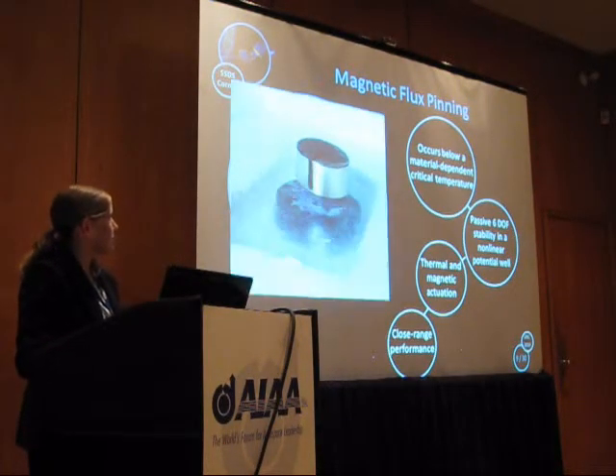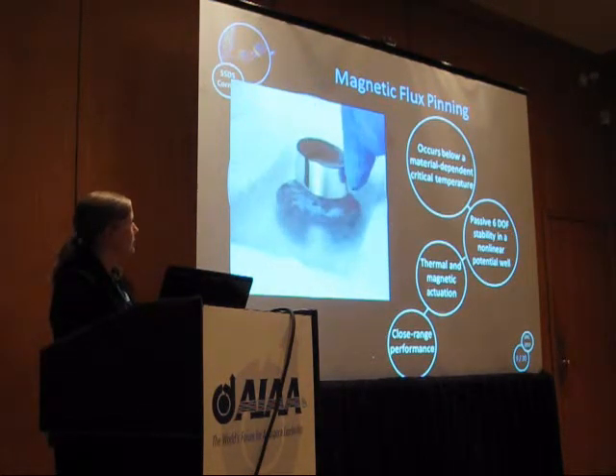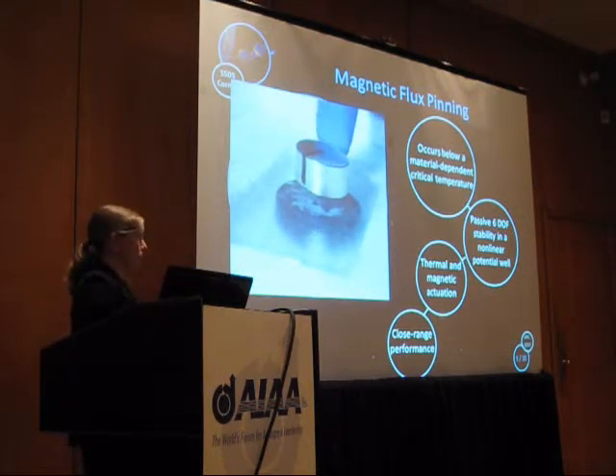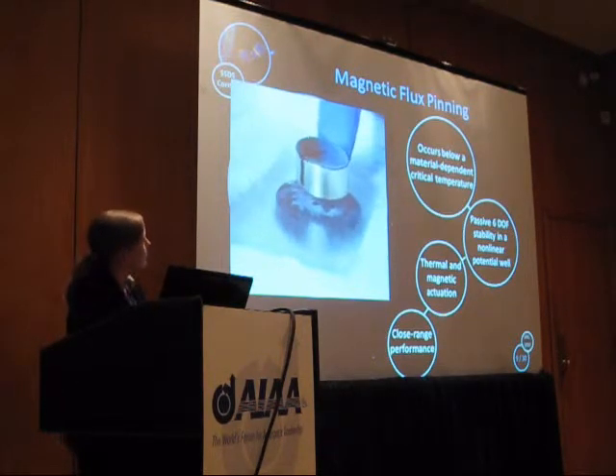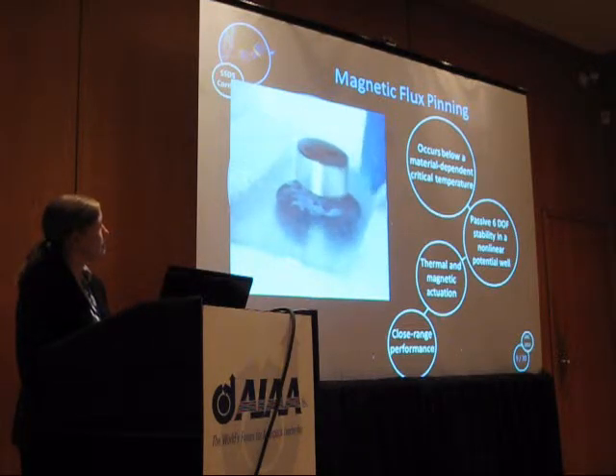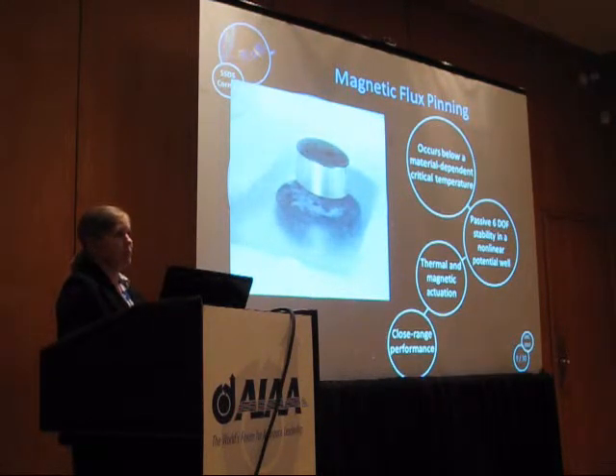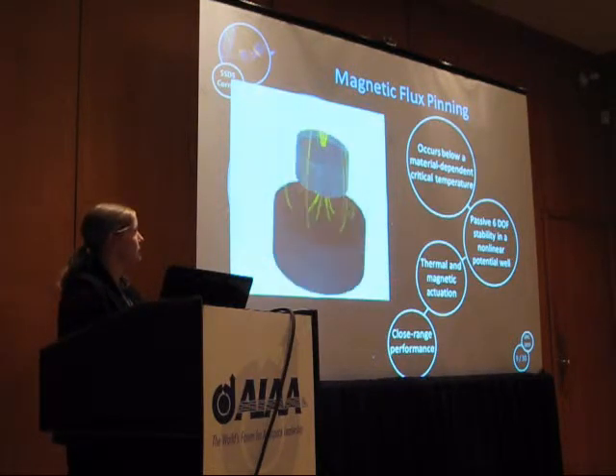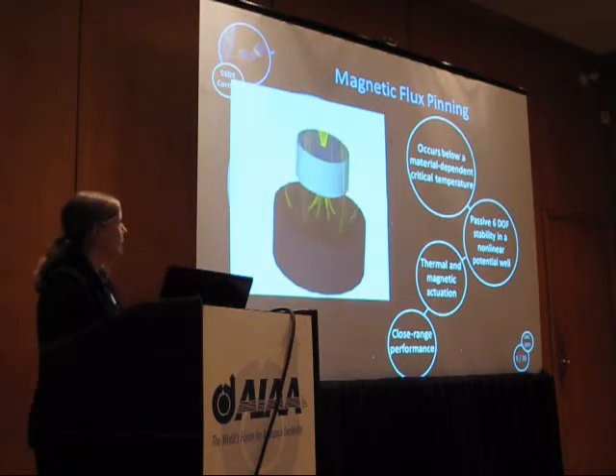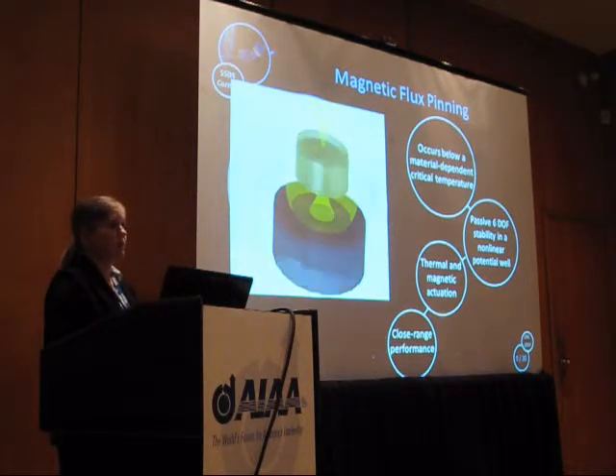The operating range is actually very close. I have a video here of a flux-pinned YBCO and magnet — this is a bath of liquid nitrogen at 77 Kelvin, well below the critical temperature. My colleague is poking at it to show significant damping in many degrees of freedom. The one exception is the axisymmetric degree of freedom — you'll see it spin, since the superconductor sees no difference in flux around that axis and so doesn't resist rotation there. For something hockey-puck sized, strong flux pinning occurs on the order of about one centimeter, with effects visible out to about 10 centimeters.